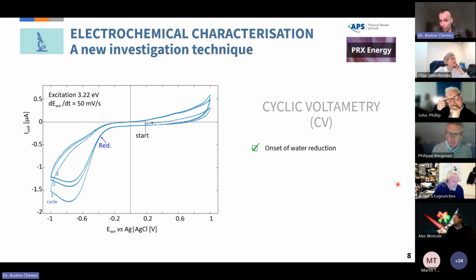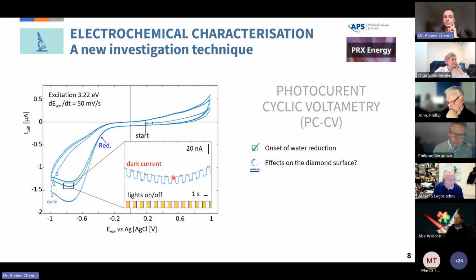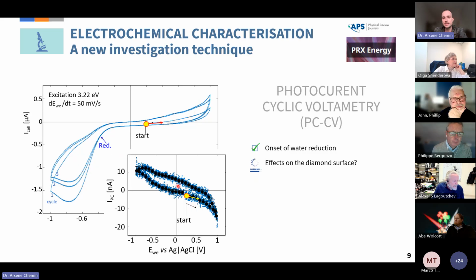And one thing we saw is that if you monitor the flat band potential along the CV curve, we can find very interesting behavior. To do that, we performed the CV curve with the light on top of it, and we extracted the photocurrent along the CV curve. When we start here at the beginning of the cycle with an oxidized diamond surface, we just move the potential, and we find at this point, at around plus 0.6 volt, the flat band potential of the oxygen-terminated surface. In that case, the photocurrent was zero for this potential.